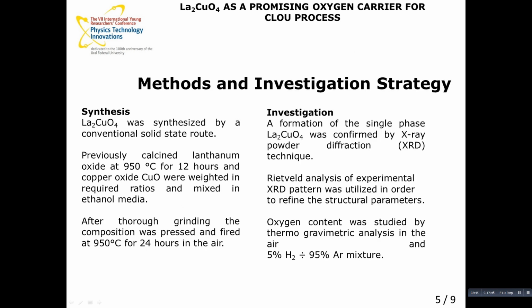High-purity copper and lanthanum oxides were selected as raw materials. Lanthanum cuprate was synthesized by a conventional solid-state route. The phase purity of the final oxide powder was confirmed by analysis of the X-ray diffraction spectrum collected using a Shimadzu XRD 7000 diffractometer. The variations of oxygen content with temperature were determined by means of the thermogravimetric method using a Setaram TG92.